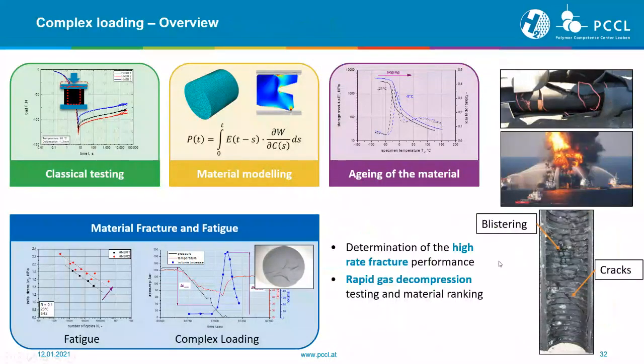And this brings us more or less to the next point, complex loading behaviors, where we are back to the oil and gas industry, where we have very complex loadings and also very harsh environments, as I showed you in the introduction. For example, here this hose failed at 1,300 bars, and nobody wants to have this burning oil rig onshore, offshore, wherever. And here we also cut a hose open where you can directly see some blistering and also some cracks inside of the material.